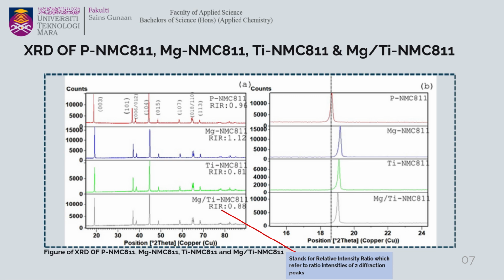And the XRD in B is the close-up data on the peak 003. So for the doped samples, the peak shifts to a higher position compared to pristine NMC. So it is indicating a confirmation that the magnesium and titanium dopants were successfully introduced into the lattice structure.